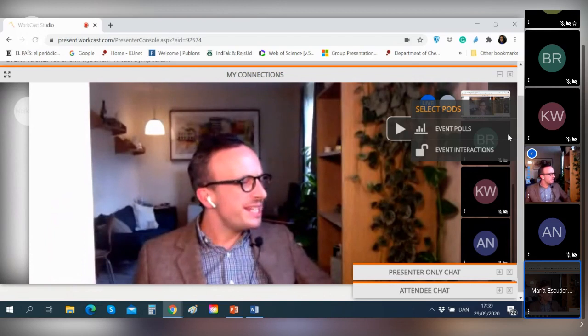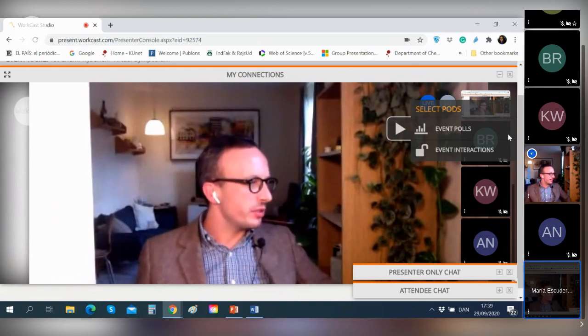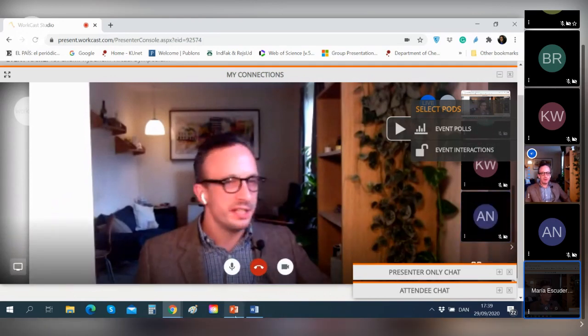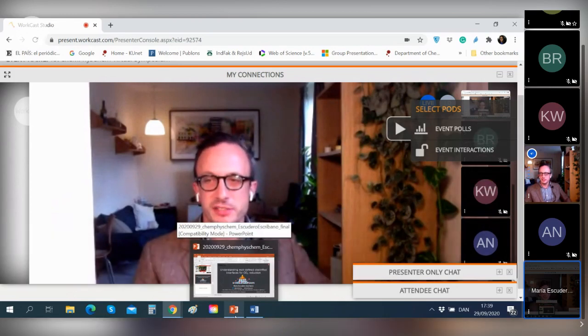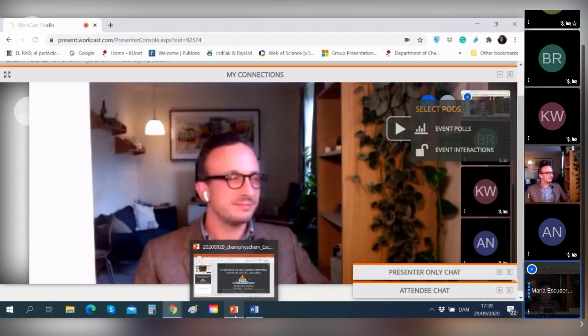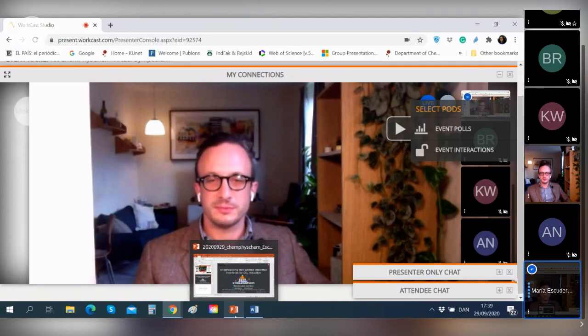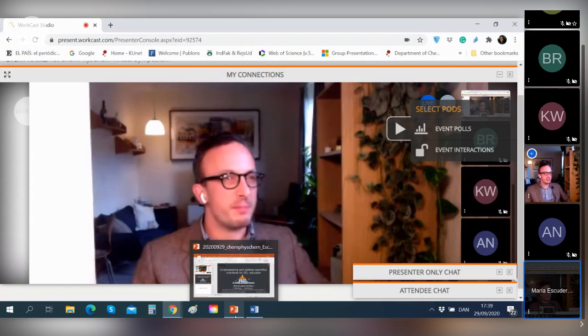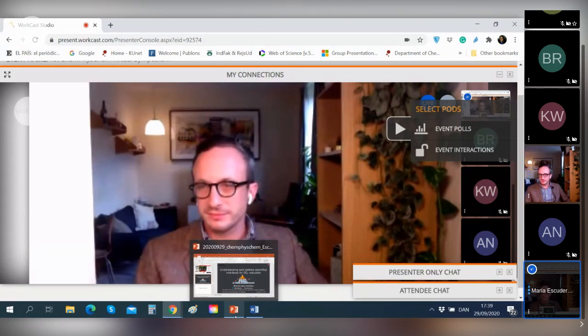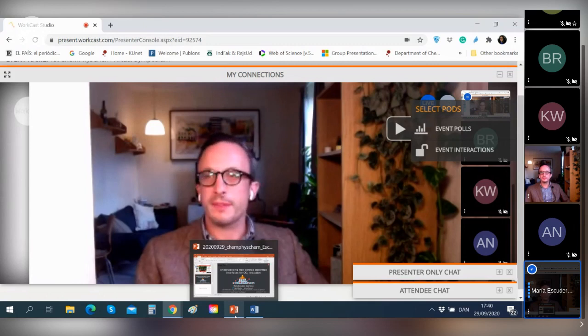And when you see the shift in the potential of zero charge between copper 1, 0, 0, and copper 1, 1, 1, how well is that captured by the theoretical calculations? This is something that, as far as I am aware, hasn't been done, and this is definitely something we want to do, collaborating with, for instance, the group of Jan, because I'm not sure that this has been studied theoretically. It must have implications not only on absorption of anions, but also on the CO2 reduction intermediates. Definitely. We are very excited because the OH absorption is clearly structure sensitive, and the potential of zero charge appears just at the onset of the OH. So that's very interesting and has implications for electrocatalysis.